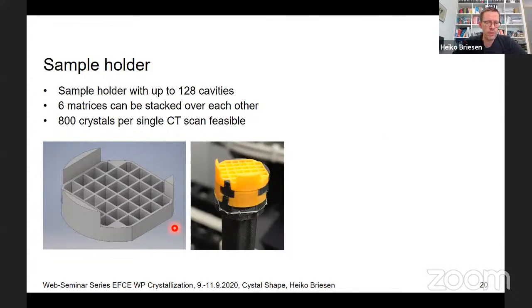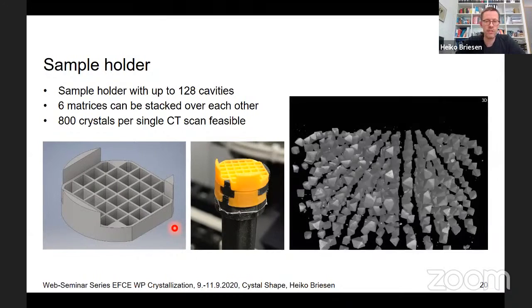What did we do? We basically used additive manufacturing and made such printed sample holders with cavities. It's still pretty painful because at the moment you still have to sort all the crystals with a tweezer into all of these different cavities. But in the end, you can at least stack these matrices over each other. You no longer have a separation problem, and with a single CT scan, you can have information on up to 800 crystals. So how does this look?